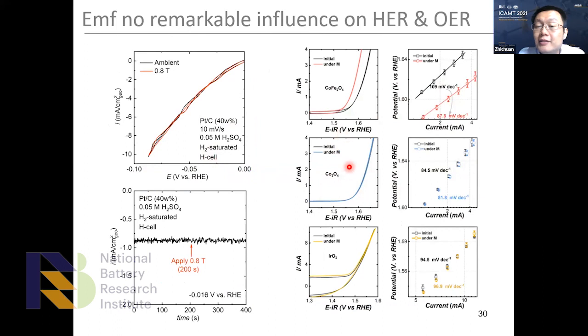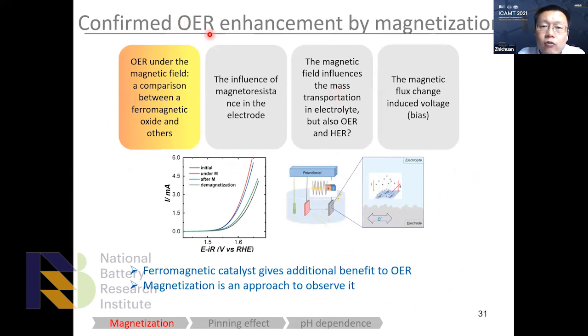Again, we would like to emphasize that we didn't observe the same on other electrodes, so we can confirm the increment on the cobalt iron oxide is indeed caused by something else, for example, the ferromagnetic nature of this material. Okay, so now we can confirm the OER enhancement is by the magnetization over here. So we can confirm, yes, that's an additional benefit from the ferromagnetic catalyst.